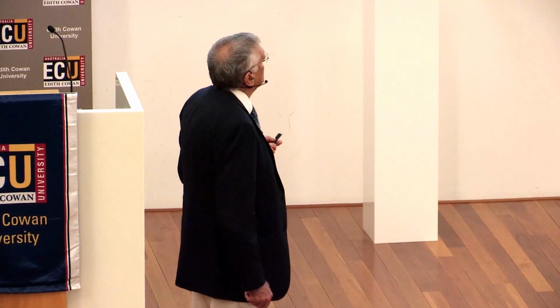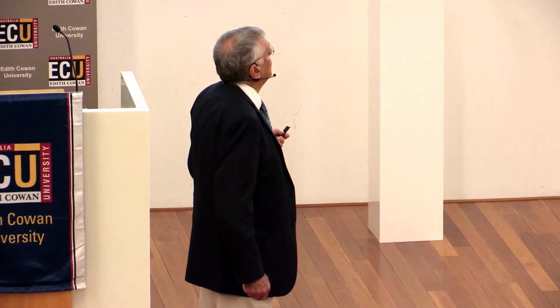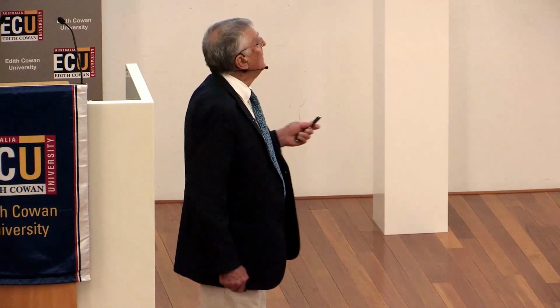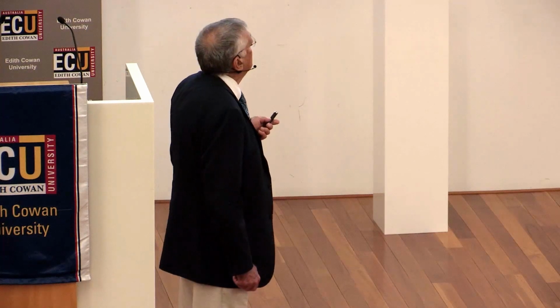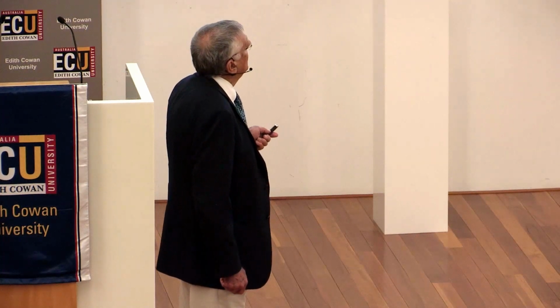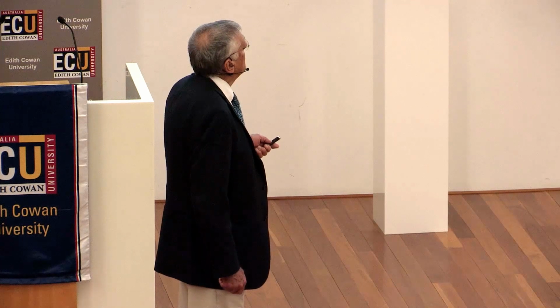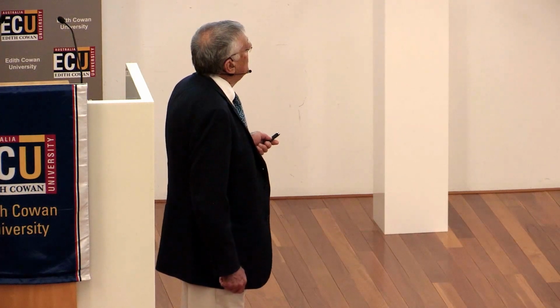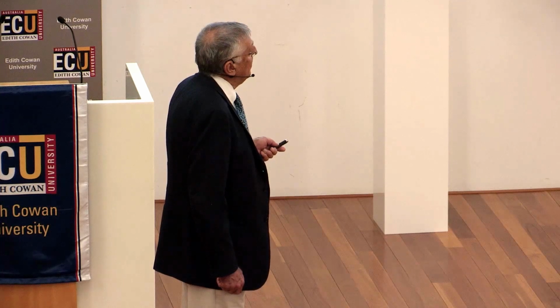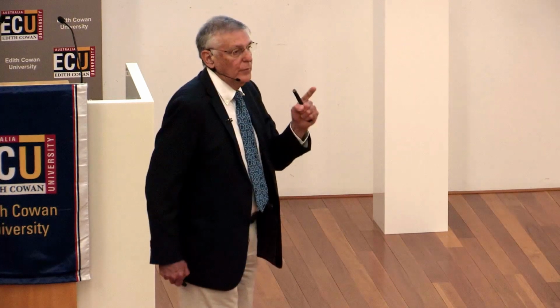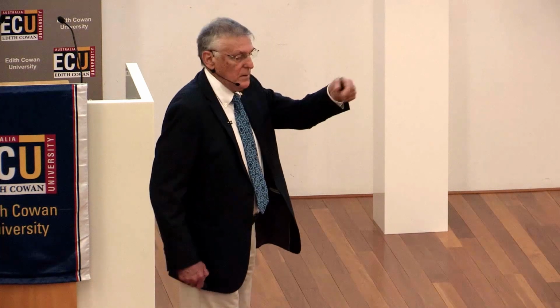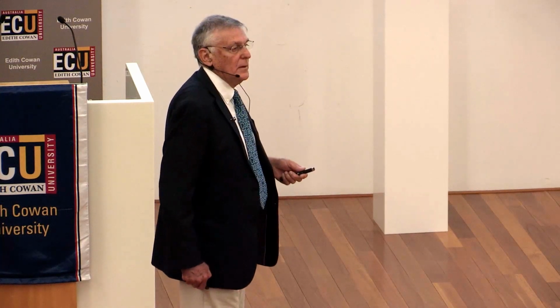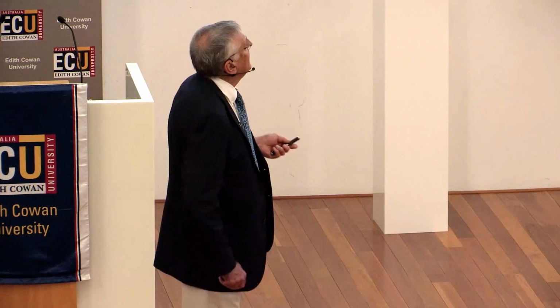So this was the electron diffraction from the icosahedral phase. This was the name I have given to the phase, and I'll tell you why I called it so. The reason is that it had icosahedral symmetry, and I'll talk to you about it. And it has a 5-fold rotation axis, and it is not periodic. So, no periodicity. By the way, it's not 10-fold, it's really 5-fold, but I should have done more experiments to see that it's 5-fold. These experiments are called Kikuchi patterns. We'll not go into that.